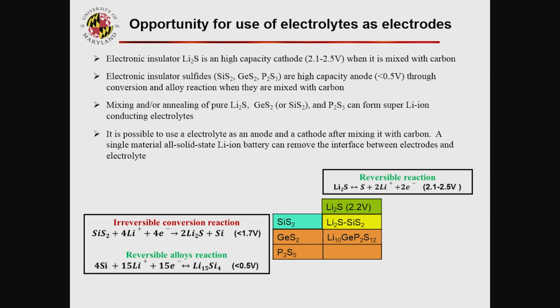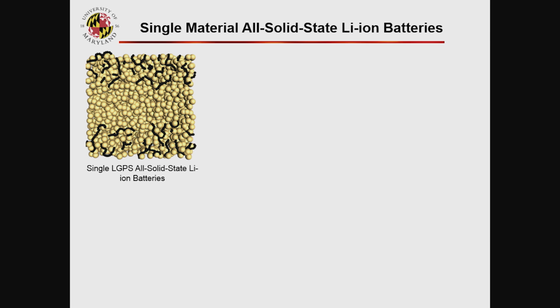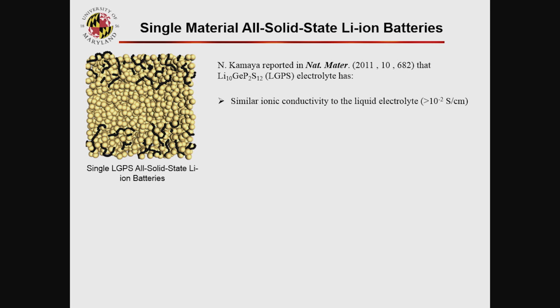So if successful, we really can make this happen. So we try. We use LGPS. We put the carbon on both sides. One side functions as anode, one side as cathode. Because they are symmetric, either side can be anode or cathode. And then we try the literature. They really report this material has a very high ionic conductivity, similar to organic liquid electrolytes.